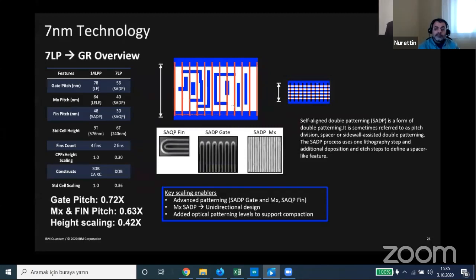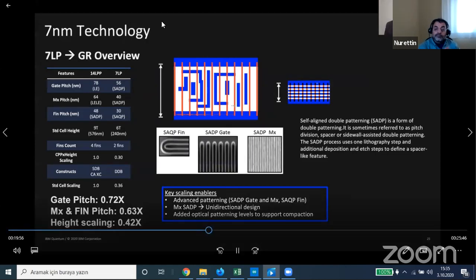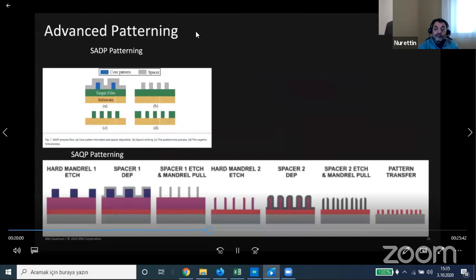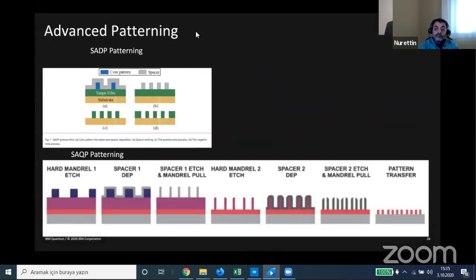Now, there was a transition point in the semiconductor industry where we went from strain, and we had to then introduce a new concept called FinFET to achieve the short channel effects necessary at smaller gate lengths. We started with the 14 nanometer process, and then we scaled that down significantly. So we scaled the gate pitch down by 0.7x. We scaled the metal and the fin pitch by 0.6x, and we scaled the cell height by 0.4x. Because we could not use EUV as described earlier for all the steps, we had to introduce advanced patterning to make the most out of DUV.